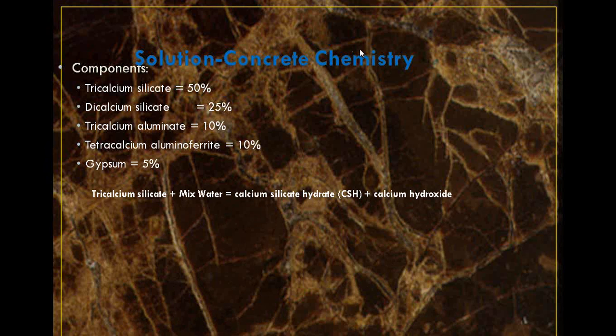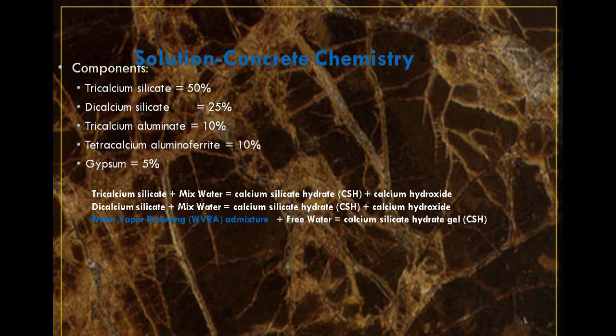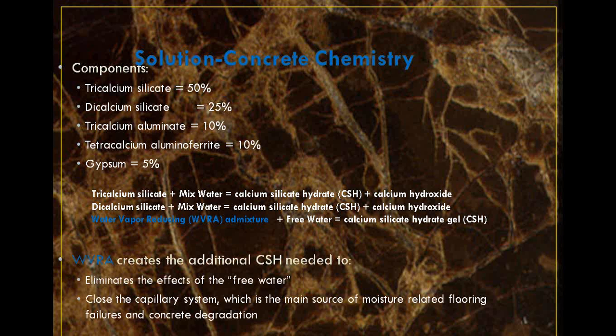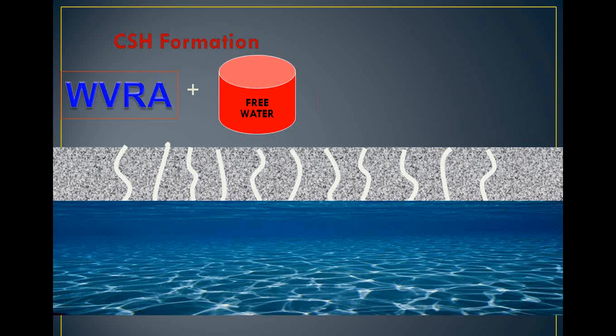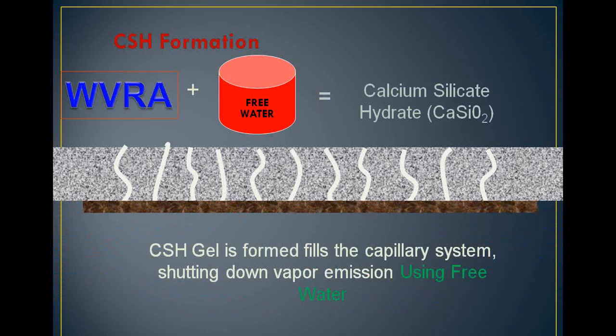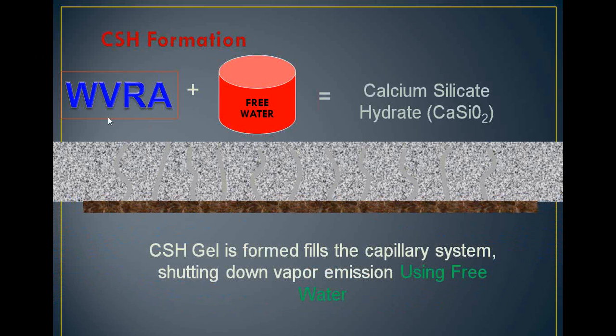So here's the solution we propose. Remember our tri- and dicalcium silicate, form calcium silicate hydrate, calcium hydroxide. Well, our water vapor reducing admixture reacts with the calcium hydroxide and the free water to form additional calcium silicate hydrate gel, where the capillaries of the concrete would be in traditional concrete. This is what it looks like. Water vapor reducing admixture reacts with the calcium hydroxide plus the free water and makes this slab impermeable. If this were your basement or your garage concrete floor, you could now take a cardboard box filled with your most precious mementos and set it on that floor, and it's not going to get damp and moldy.